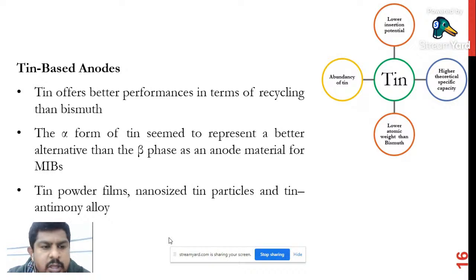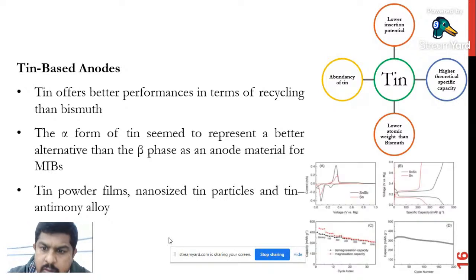The kinetics got improved in the anode because of these alloys. This is a graph, I think you guys can see it. The first one is that the kinetics gets improved. See this black one, there is an increase in the kinetics here. And in SnSb, if you see this, the energy capacity increased when you compare with pure tin. Then the rate capability and the energy storage retention are also comparatively more when we compare with the pure one.